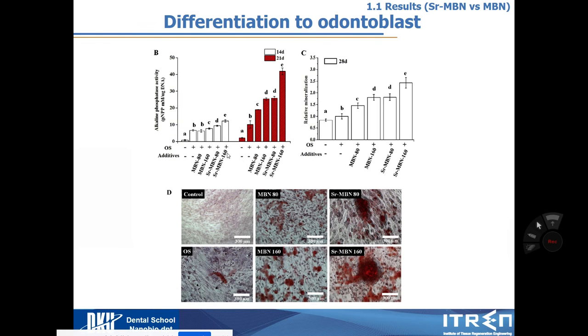And then I want to check, previously I checked the gene expression, but genes should be translated into protein and the ECM. So this is some outcome of the protein, ALP, which means alkaline phosphatase. And then the images below show the calcium deposition by ARS staining. When you say dentin, the composition of dentin includes maybe 90% hydroxyapatite. Hydroxyapatite is composed of phosphate, calcium, and hydroxide. So ALP is measured by the phosphate, and ARS staining can measure the calcium deposition on the cell.